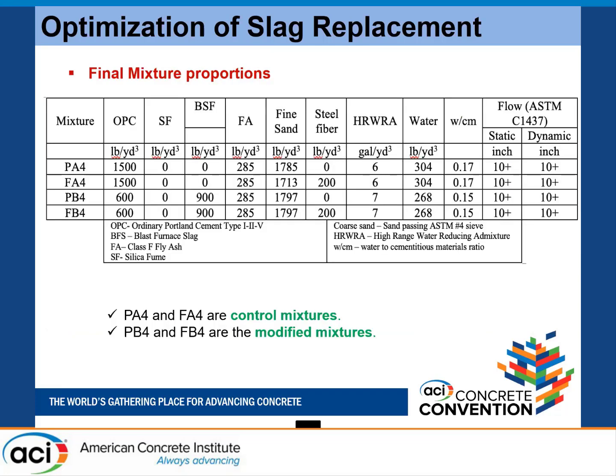Then there are some mix designs here. I'll explain a little bit. PA4, FA4: P stands for plain UHPC, F stands for fiber reinforced UHPC. Another improvement we made in these UHPC mixes is that in typical UHPC composition, sand is sieved through ASTM number 30 sieve, with a particle size range from 75 to 600 microns, which is not a sustainable practice, because scalping of sand through the number 30 sieve is a labor intensive process. Plus the material that is retained on top of the number 30 is just a waste. So it's not a sustainable practice.